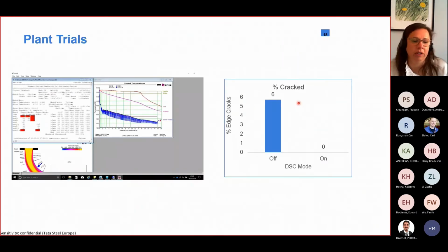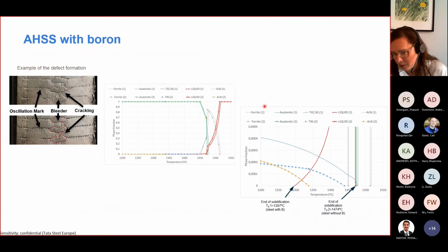That particular case was done for one of our casters in Tata Steel, India. Based on that, collecting all that information together with them, we redesigned the cooling of the caster in order to reduce the cracking susceptibility. Now, the results speak for themselves. If we add the dynamic cooling as we redesigned it, we don't have any cracks. If we have the old cooling, we have a lot of cracks. So the result speaks for itself.